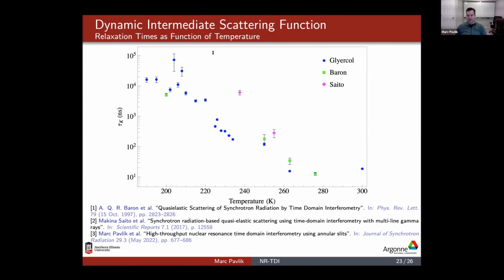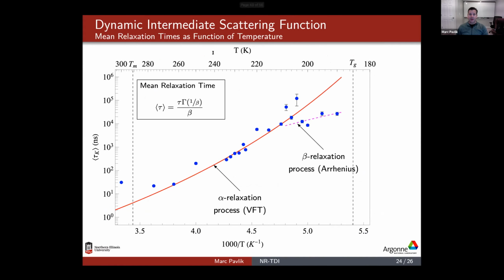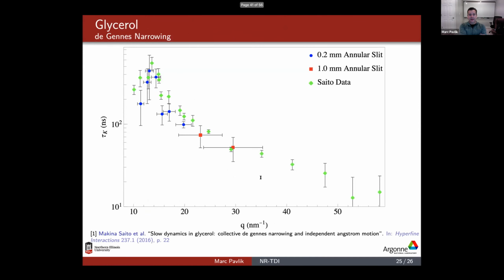This is just the different relaxation times for the Q values. We can do the same thing for the different temperatures. As we go from a warmer temperature to a cooler temperature, the molecules again start to bind up. So this is just a plot of them at different temperatures. We can see we agree reasonably well with other literature out there. And if we look at the mean relaxation time, we can start to look at the different alpha and beta processes of these 2. And finally, for glycerol, we were able to do a de Gennes narrowing on that using the smaller annular slit. Again, it agrees reasonably well with other data out there.